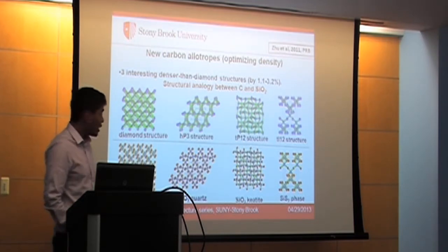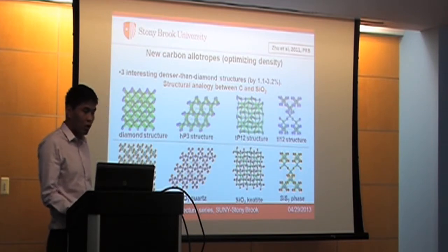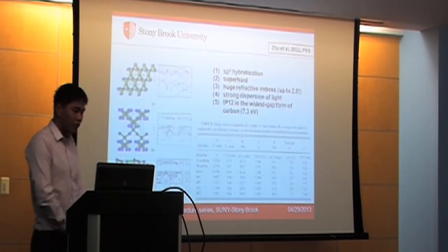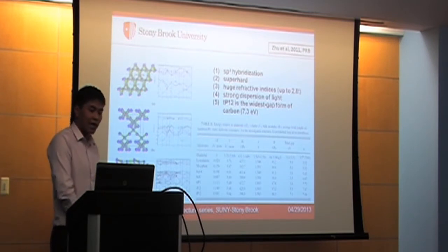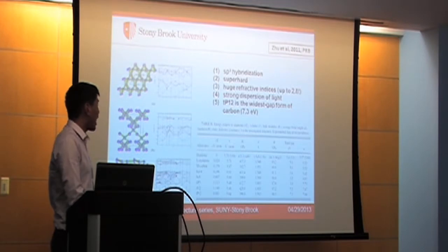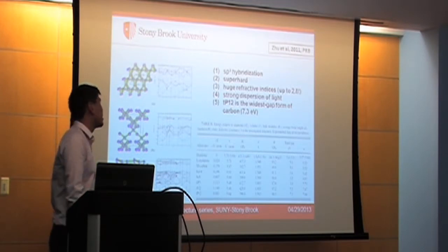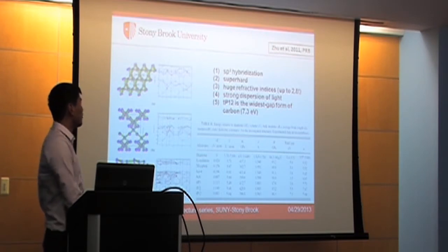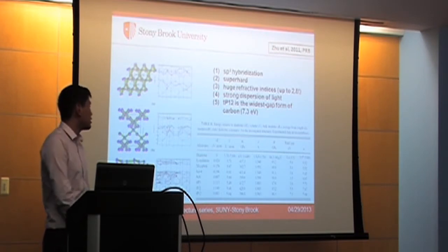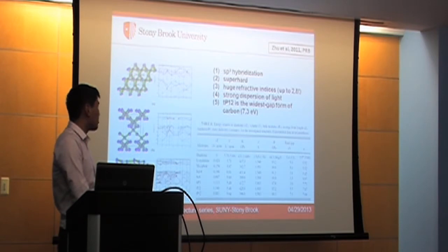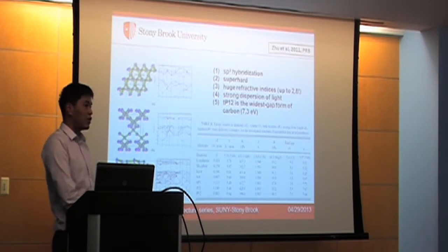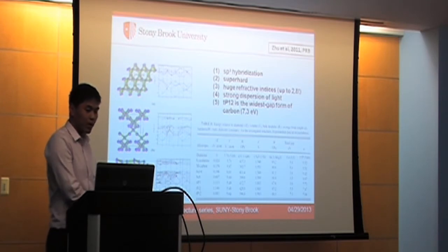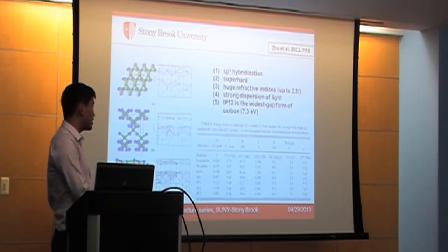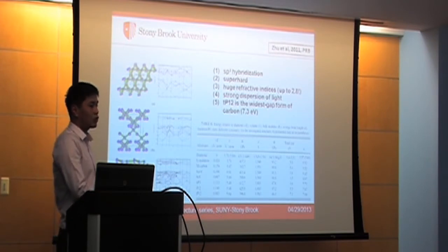silicon oxides. And these structures are interesting not only because of the density, but also because of some other physical properties. For instance, they are mechanically also very hard. The hardness is comparable to that of diamond. And they have very fascinating optical properties. One is the strong dispersion of light. All of these structures have stronger dispersion of light than that of diamond. As we know, diamond shines because of the strong dispersion of light. So it means that if we can synthesize one of these structures, this material will even outshine diamond.